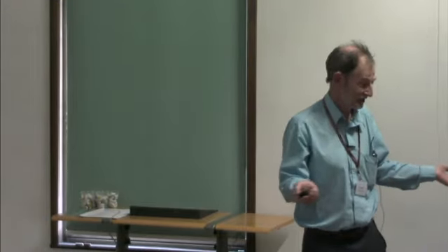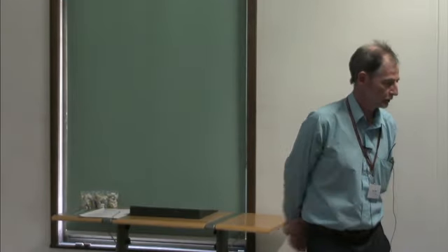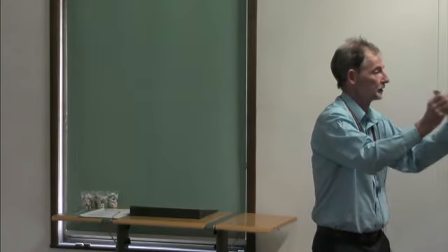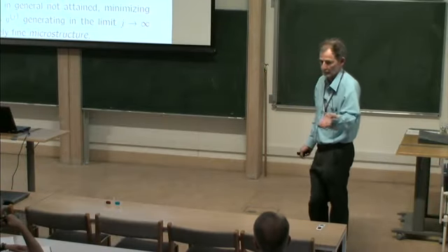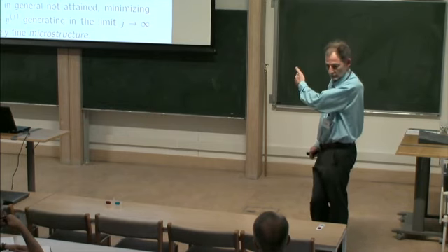Well, there's first of all the definition. Then there's saying that it's Jensen's inequality. When you say there's a geometric picture, one of the problems with quasi-convexity is that we don't know how to tell whether a given f is quasi-convex or not. I'm not sure what kind of geometric picture you're thinking, but the most primitive way of thinking about it is, I've got this material, I specify linear boundary data. It's quasi-convex if the minimum energy is just linear, and nothing more complicated happens. And that's the difference between something like rubber in usual deformations and something like these materials.